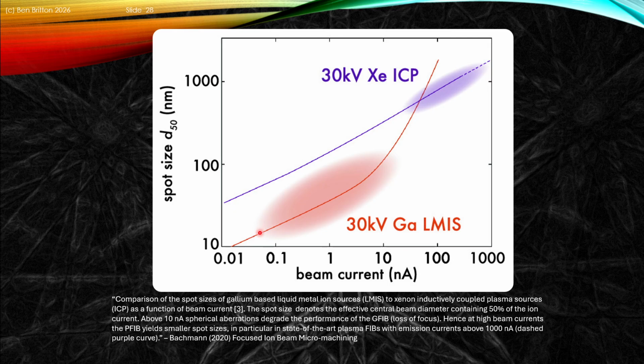In this case, we see that typically for most gallium systems, there is this sort of sweet spot of a beam current between, say, 100 picoamps or down to 10 picoamps, up to, say, 10 nanoamps or so. And here we get a relatively linear spot size with current domain. We notice that the spot size is typically a lot smaller for our gallium FIB. That enables us to be more precise in how we cut objects as we're FIBbing them.